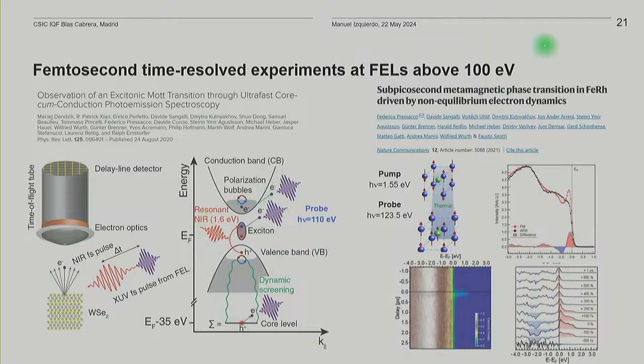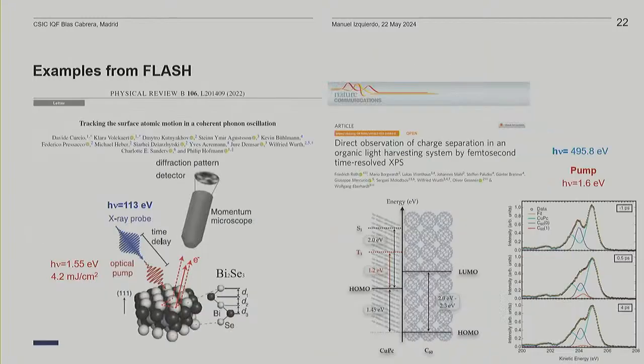So it has been also used to study phase transition. This is a very classic example of the antiferro to ferromagnetic transition in iron rhodium. This was done already above 100 electron volts, so overcoming what is available with high harmonic generation sources. It has been used to do the first photoelectron diffraction experiment, on bismuth diselenide. And also to study charge transfer in light harvesting materials.